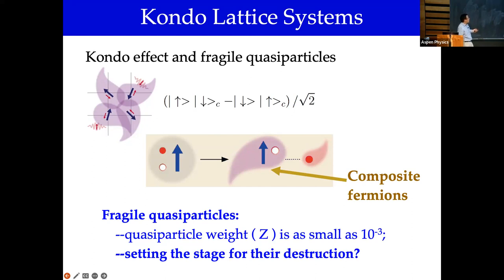I already mentioned that there's an antiferromagnetic exchange interaction between the spins, the local moments, which are these black arrows, and the mobile electrons, which are these red-purple ones. And they form a spin singlet, up-down minus down-up. That's a maximally entangled state. Now, you can think of this spin singlet as a bound state of the spin, which creates spin-one excitations coupled to the spins of the electrons. In semiconductors, you may have heard the word exciton. An exciton is a particle-hole combination of electrons in the triplet channel. If that's the bound state formed in the ground state, then following the rule of Feynman, we can think about excitations by just breaking what's in the ground state.